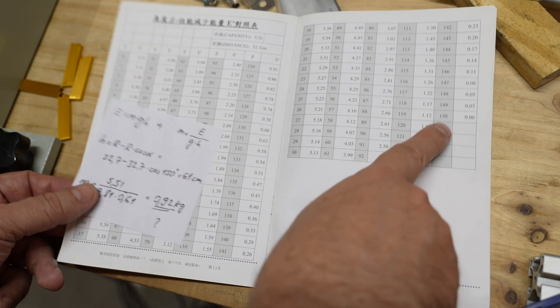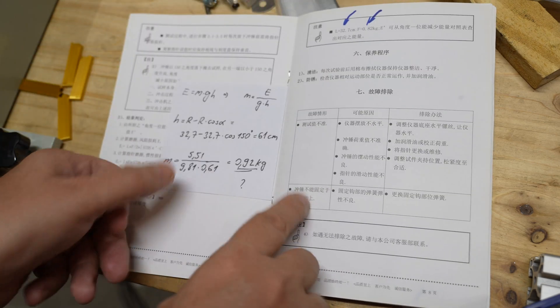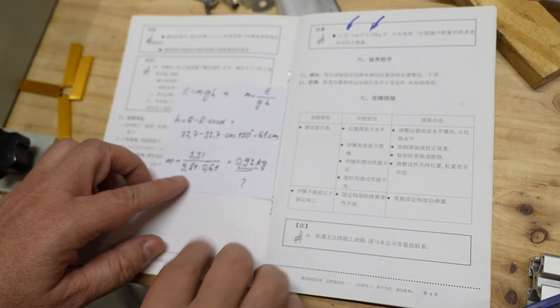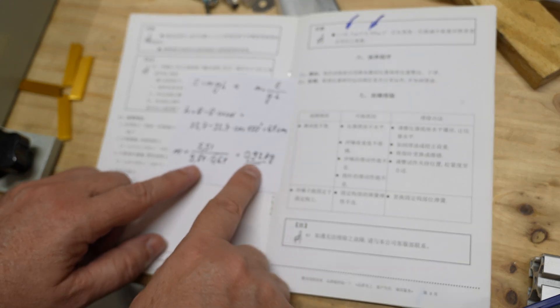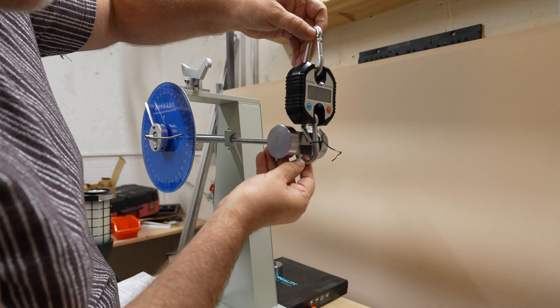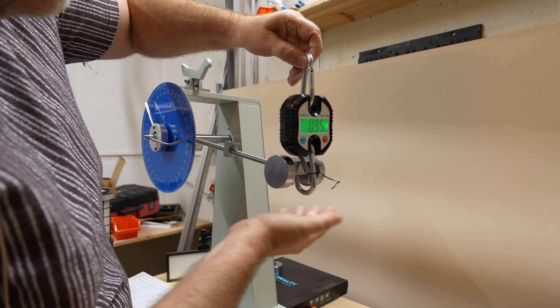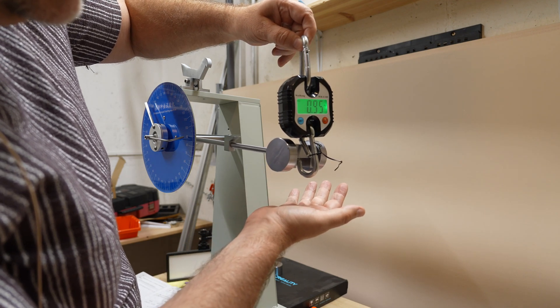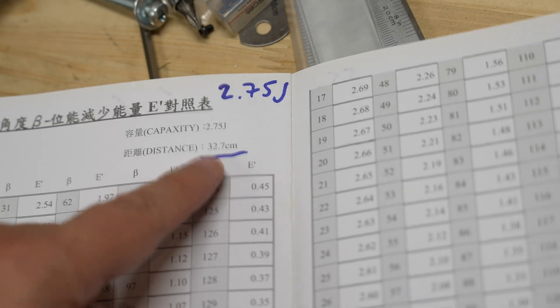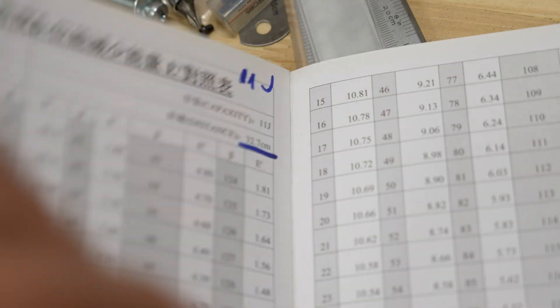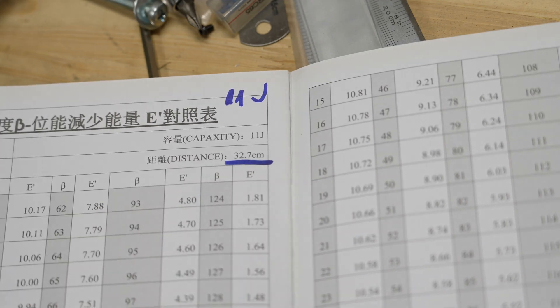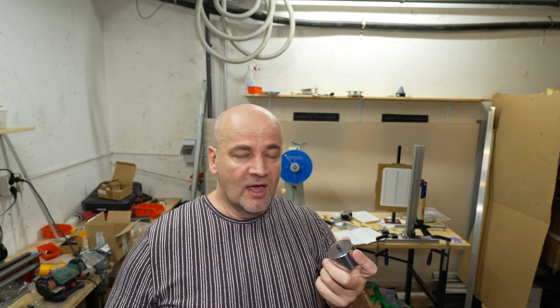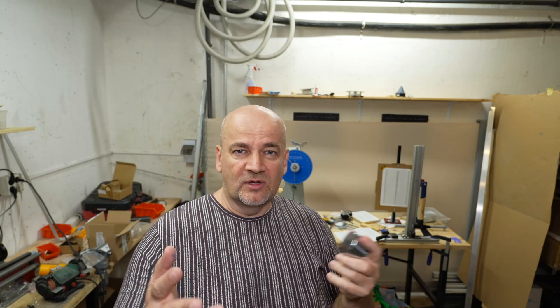I have some problems with evaluation of data using their tables. I checked the numbers and I can find some confusing numbers. For example, I checked 5.51 joules for 150 degrees and I didn't get 0.82 kilograms in my calculation. I got 0.92 kilograms, and I measured the weight approximately and I measured 0.95 kilograms. So that is closer to my calculation. It looks like this is that price difference we have to pay between cheap Chinese and expensive European machines.